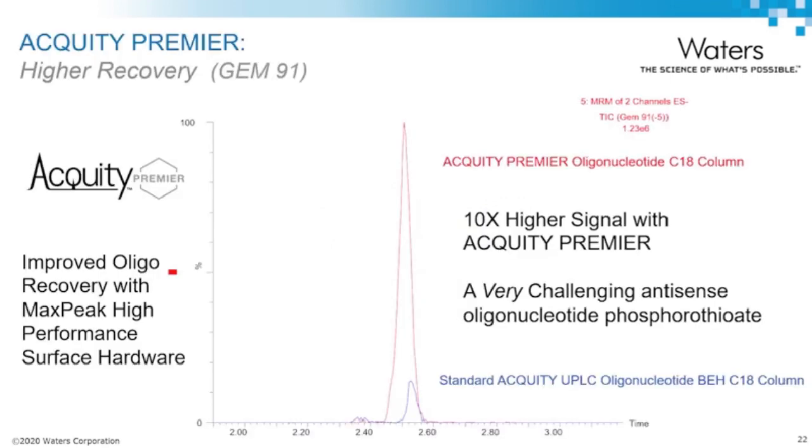So here on slide 22, I show you bioanalysis of oligonucleotide. And if you remember, as I earlier mentioned, that sample conditioning of frit and metal surfaces takes longer time when we inject low mass load of a sample on the column, and it is faster with higher mass load. This is the case for bioanalysis with sensitive LCMS applications when we inject sub-picomole amount of sample. It takes really long time to condition the column, and even when fully conditioned, you may still get lower recovery of the sample than is desirable.